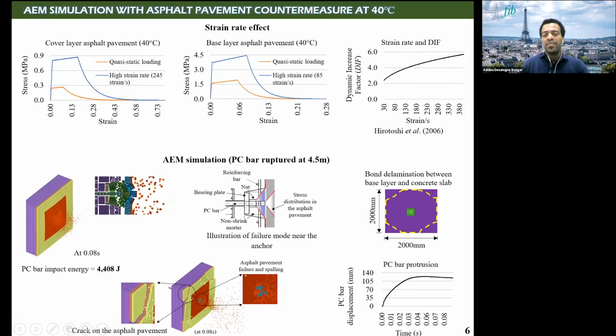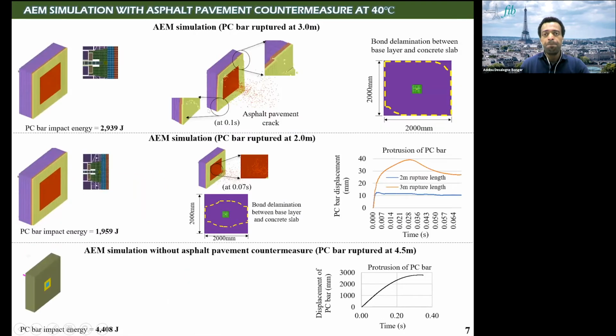Anyway, at this temperature, when the bar impact energy is 4,400 Joule, the pavement system was not effective according to this numerical simulation. So we extend the numerical simulation by reducing the impacting energy. We just change the rupture distance to 3 meters so that the PC bar impacting energy becomes around 3,000 Joule. So this time